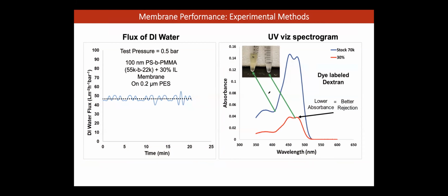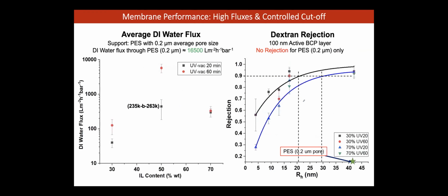And then, as I said, chemical interrogation is important for membranes. So for example, we have a dye-labeled dextran. Dextran is this large carbohydrate molecule. And we can study what comes out of the filter membrane. You can see that, for example, the red one is a lower intensity. So that means the dextran was rejected by the membrane compared to the blue one. That is just an illustration of the kind of things we do.